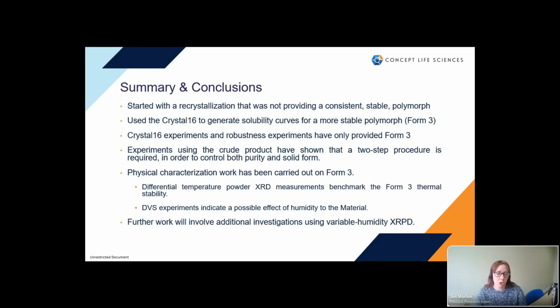Experiments using the crude product have shown that we need a 2-step procedure in order to be able to control both the purity and the solid form of the material. We've done some additional physical characterization work on form 3, XRPD measurements to benchmark the thermal stability, and some DVS, which shows that we might have an interaction with humidity. And so further work on this compound will involve additional investigations. We'd like to do some variable humidity XRPD to fully investigate what's happening there.